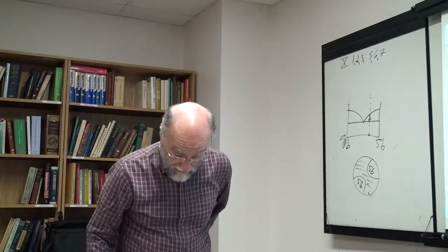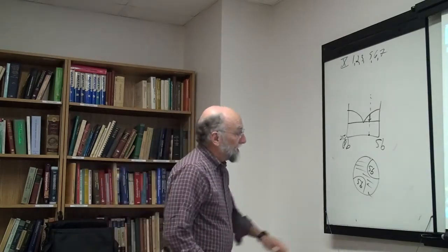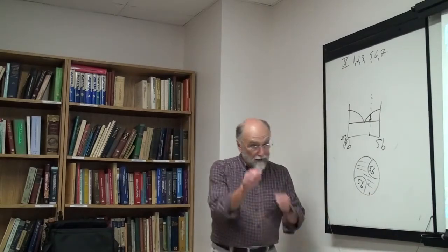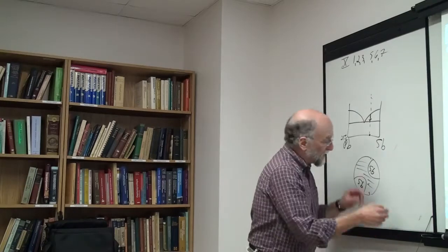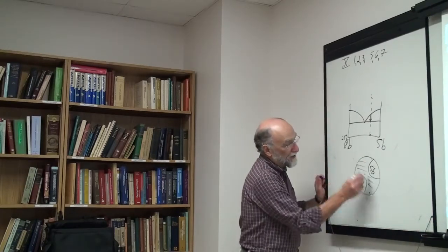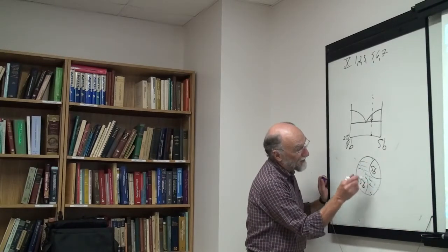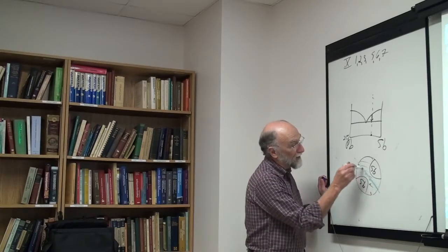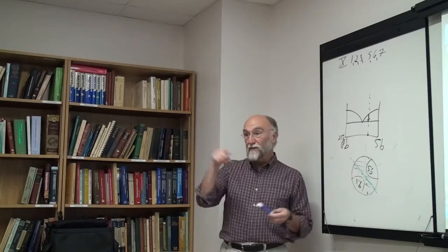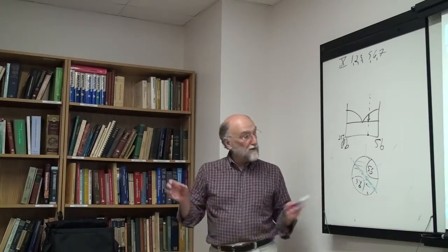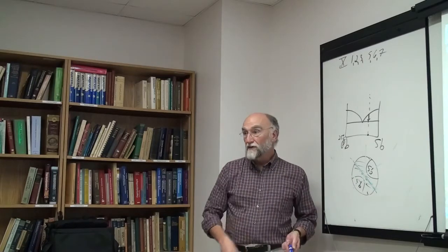Okay, and what they do is then you put this in a microscope. The microscope has a little grid across it. You measure across this diameter, you take a few diameters across here and measure what fraction of each diameter is covered by the eutectic and by the antimony. And taking the average from this, you can work out the volume fraction. Or generally there's software now that just looks at the two images and works out the surface area for you.